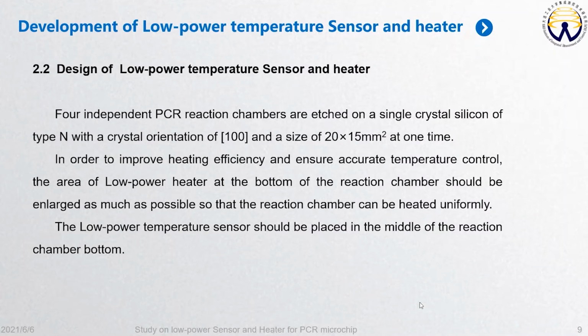Next, we will give the design of low-power temperature sensor and heater. 4 independent PCR reaction chambers are etched on a single crystal silicon of type N. In order to improve heating efficiency and ensure accurate temperature control, the area of low-power heater at the bottom of the reaction chamber should be enlarged as much as possible so that the reaction chamber can be heated uniformly. The low-power temperature sensor should be placed in the middle of the reaction chamber bottom.